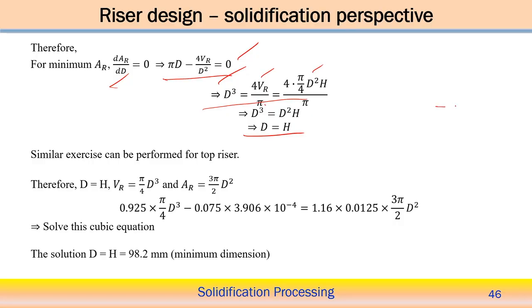So this is the side cylindrical riser, but a similar exercise can also be performed for the top riser. In the case of the top cylindrical riser, there are three surfaces responsible for the heat transfer, but one is in contact with the cast volume. So we need to consider only these three surfaces, therefore pi d h plus pi by 4 d square. So instead of 2 into pi by 4 d square, the surface area will be different in the top riser case, and we can perform the similar exercise to minimize the surface area and find a different relation between d and h.